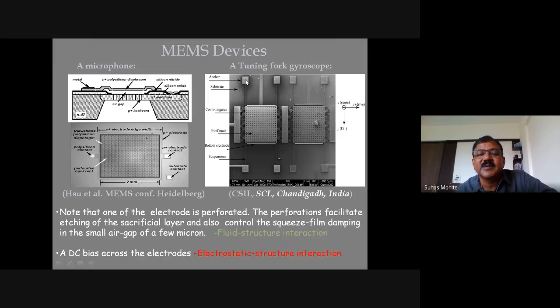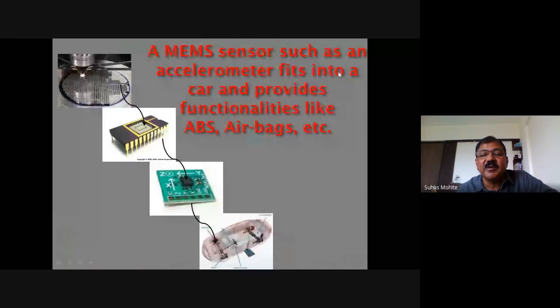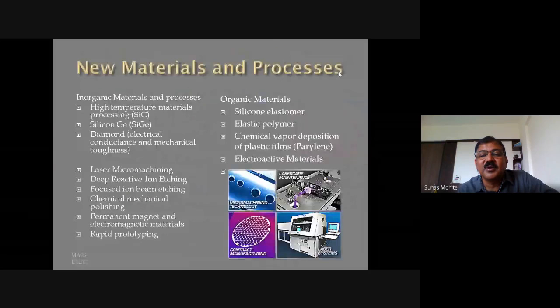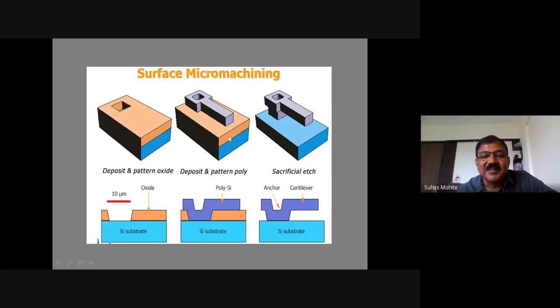These are the anchors. Shall I go back to the earlier picture that I showed you? This one. Now look at this. This was the sacrificial layer. Now this sacrificial layer has to be dissolved. So that means the etchant has to go underneath this and etch out. Now this being a cantilever, there is no problem. But if this were a plate, then the etchant has to go through, and this particular gap is very small. Remember, this particular lateral dimension is several hundreds of microns, whereas this particular thickness is only 2-3 microns. And therefore, the etchant has to go laterally underneath the top plate, top layer rather.